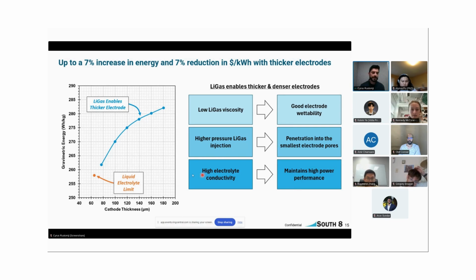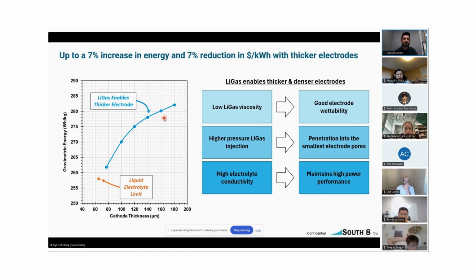So this chart on the left is showing your cathode thickness, and you would pair that with an anode, of course, of appropriate thickness. Your liquid electrolyte is limited to about 60 to 80 microns. But with our liquefied gas solution, we've modeled it out. If we can bring this up to about 180 or 200 microns, you can see how the gravimetric energy follows this curve here. We can offer a considerable improvement in energy just by thickening up that electrode, which also reduces your cost at the end of the day.